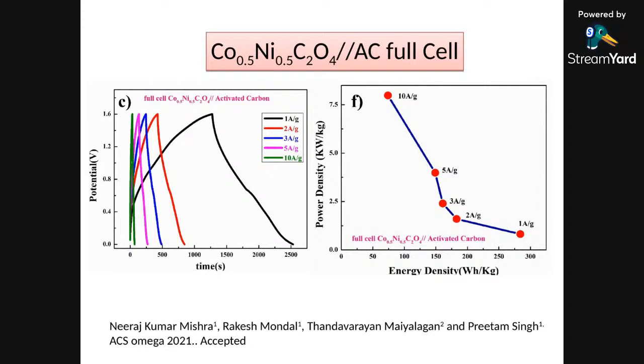And then we have done the full cell test using the cobalt and nickel. And what we find is, even up to 10 ampere per gram current we can charge it. So see, now the charge and discharge can be done at a much higher current rate, and even at the 10 ampere per gram current rate we are getting close to 70 watt hour per kg energy density. If we compare with the cobalt oxalate, at 5 ampere current density, now we can get even 150 watt hour per kg and around 3 kilowatt per kg in terms of the power density. So see, this framework has been improving continuously.